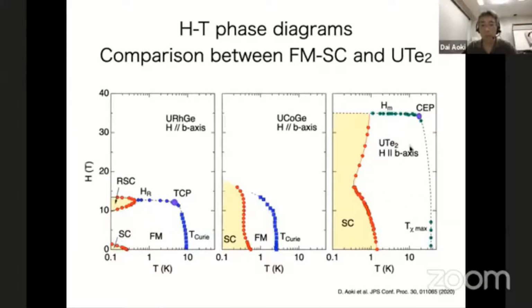But in the case of uranium ditelluride, there is no Curie temperature. Instead of T Curie, there is T chi max. This is the crossover, a broad anomaly of the susceptibility. So this is connected to the first order transition at HM. And up to HM, superconductivity appears like this.